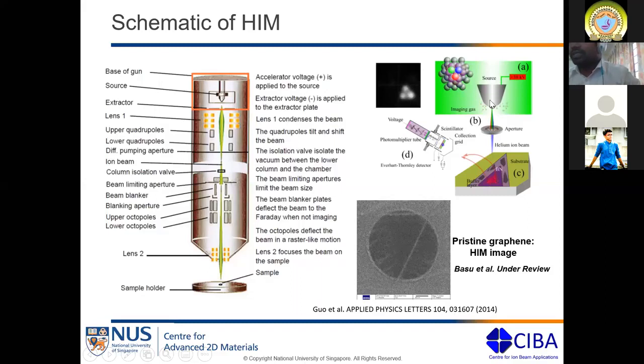So if you look at this schematic here, this ion beam, which is coming out from this single atom, passes through different kinds of apertures, and then interacts with the sample and gets detected in the secondary electron detector. This is an image of a freestanding graphene membrane on a 1.2 micron hole. This is freestanding graphene, which I talked about earlier, and you can see this line which diagonally connects the periphery of the hole. This is actually a fold.